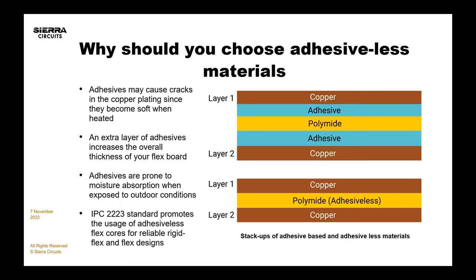Adhesive can cause all sorts of reliability issues, so just be aware whether you're using an adhesive-based or adhesiveless material set. For example, when you're trying to clean the inside of a via using a plasma, that adhesive may react differently than the other materials in your stack-up — especially in a rigid flex stack-up. You have to be careful of reliability concerns like wicking, proper etch-back, and any sort of dendrite growth that can happen.